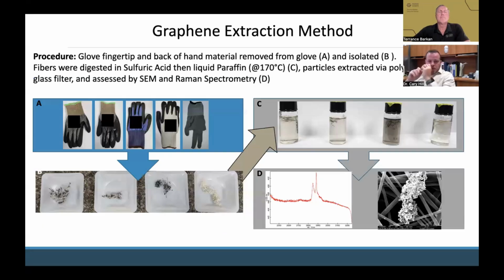Next slide. So our extraction method, in a nutshell, what we've done is we've taken the gloves, we've extracted the fibers, we've cut swatches, we've analyzed the fabrics as received, the rubberized material as received, and then also performed these digestions. More details are available in that publication, but succinctly, we would start in fully concentrated sulfuric acid. Depending on the composition of the fibers, that may be sufficient to dissolve the fibers if they're nylon-based, for example. Others that may be like HDPE-based Spectra, that kind of thing, require a different extraction method with liquid paraffin at elevated temperature. All the details are in our publication. If you want the specifics, we can make sure you get them or you can find them there. And then we filtered the material to observe any captured particulates and performed our compositional analysis from there.